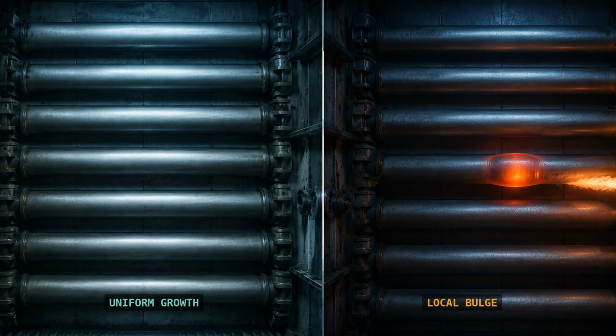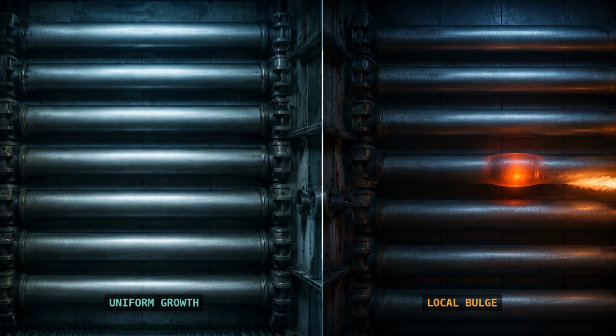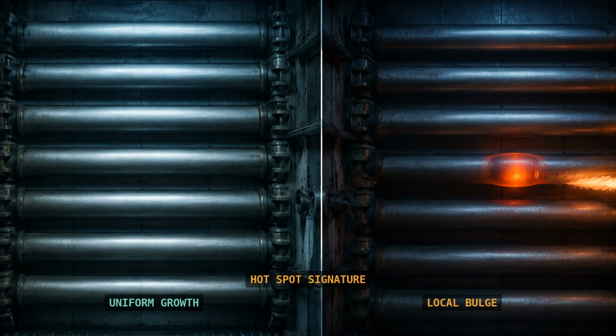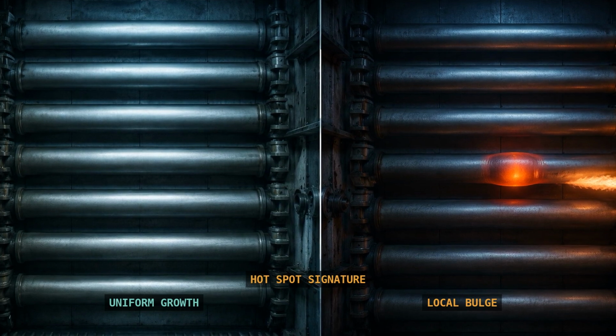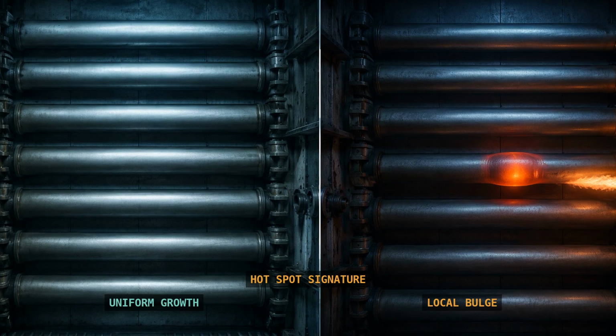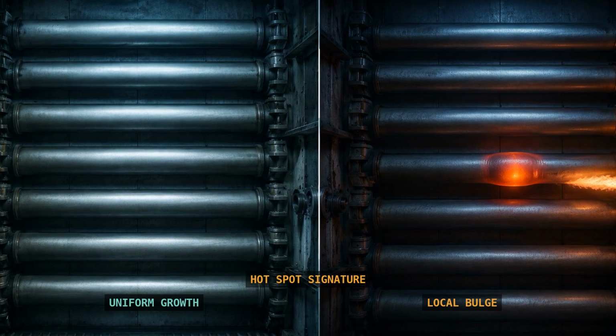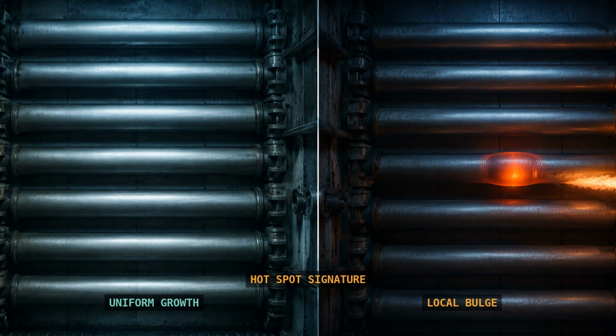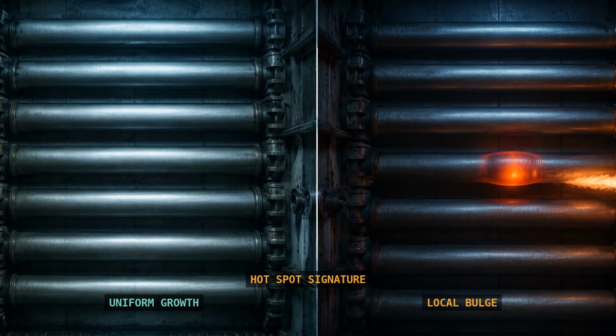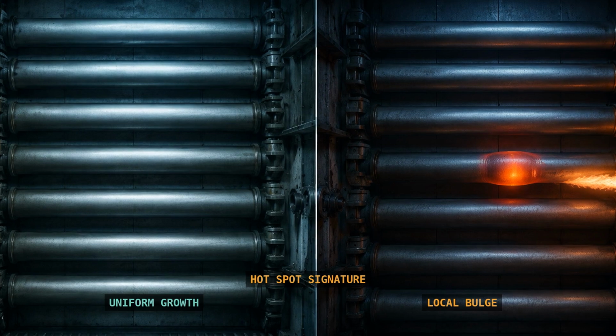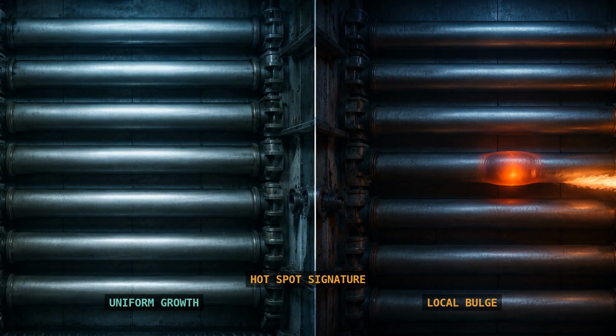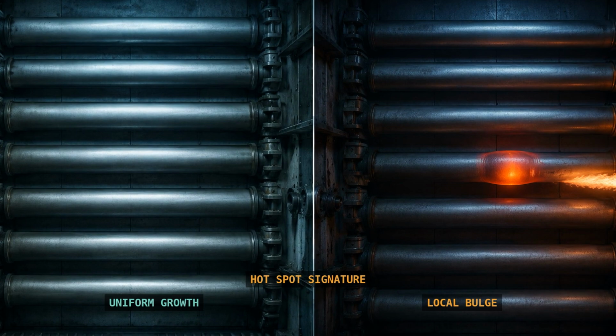Over years of service, every tube in the hot zone accumulates a small, roughly even diametral strain. That's uniform growth, expected aging. Gradual, predictable, trendable. A localized bulge is something else entirely. One spot, one tube, growing much faster than its neighbors. The signature of a local hotspot, and it always has a cause.